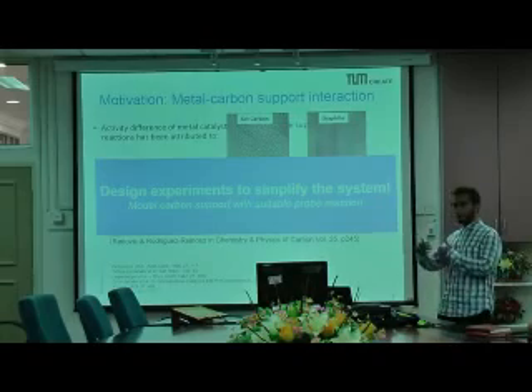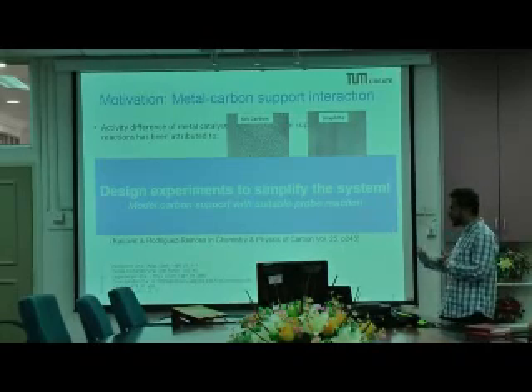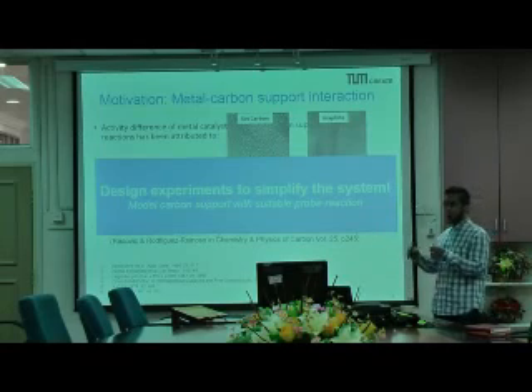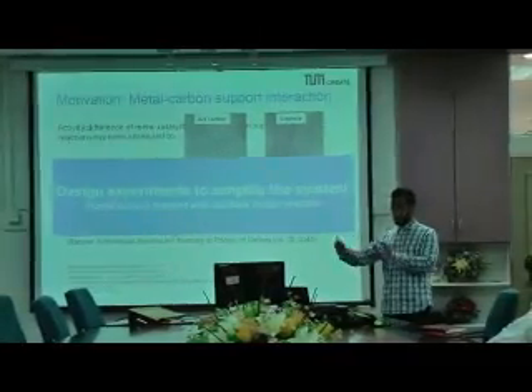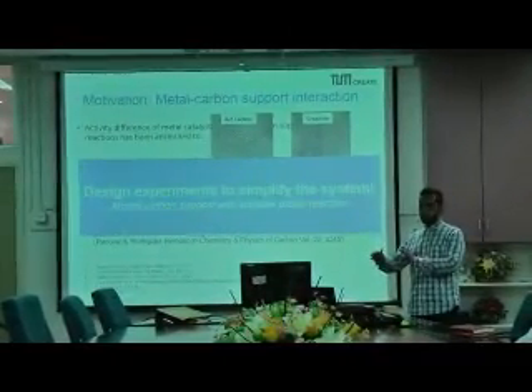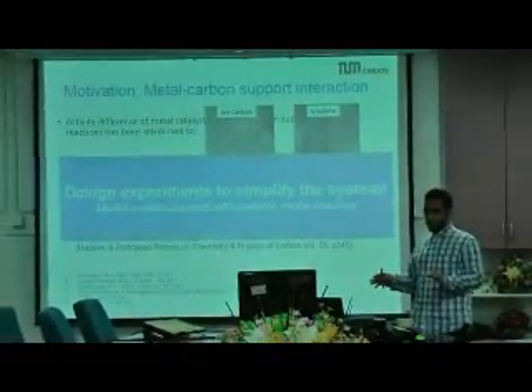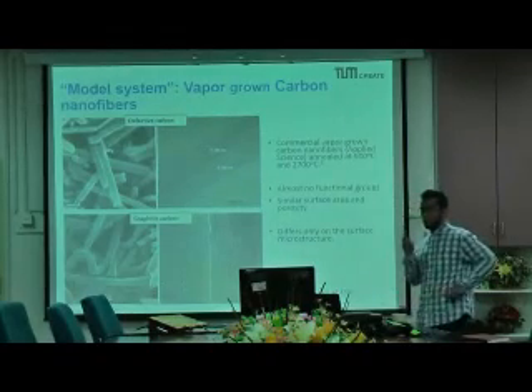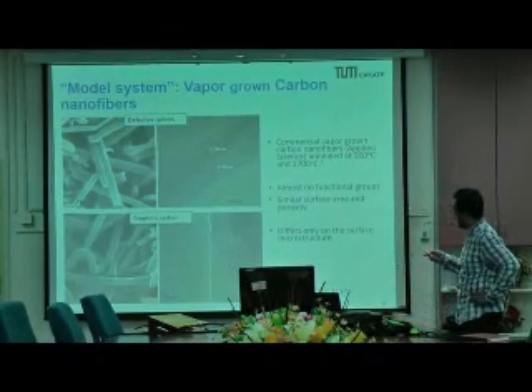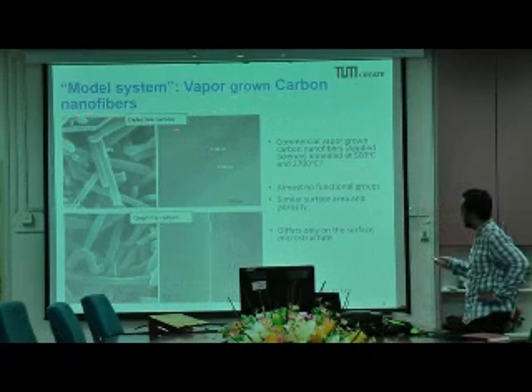So when you're faced with this kind of problem, to move forward you have to simplify the problem, and you want to design an experiment where the reaction mechanism or the reaction conditions are simple enough to understand later when you see the results. And we use a model carbon support with a suitable probe reaction. So the model system that we use is a vapor-grown carbon nanofiber. This is available commercially.